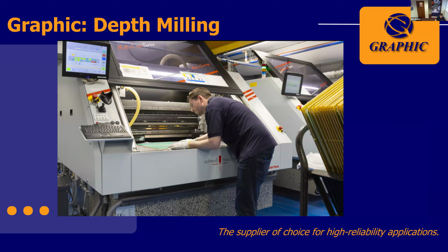So these machines are very specialized when it comes to depth milling. They have an accuracy of plus or minus 13 microns. Now that accuracy of the machine is only as good as how flat a PCB is when we put the panels onto the machine. The flatter the PCB is, the more accurate we can be with the Z-axis depth milling process. So this is why we always say to designers, if you can flood fill your signal layers as much as possible, then that always ensures that you get nice surface topography. You don't have any height discrepancies across the panel, which then allows our depth milling accuracy to be even more accurate.